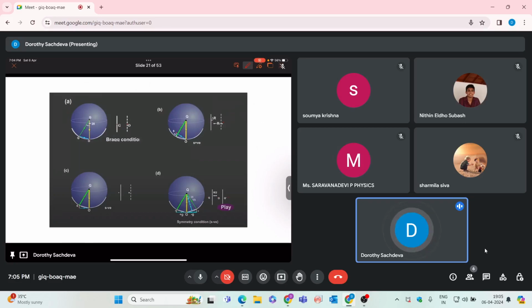So this is the exact Bragg condition, where this is your direct spot at O and this is your diffracted spot. In this case, you won't see any diffraction pattern on your screen. But if S is positive, that means it is inside the Ewald sphere, and S negative means it is outside the Ewald sphere. Then it will be shifted from the direct beam.